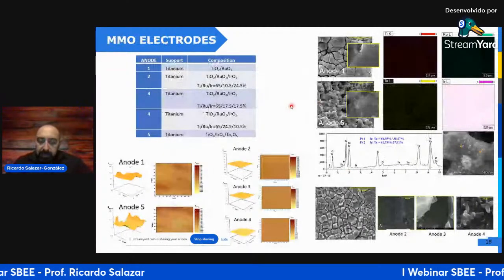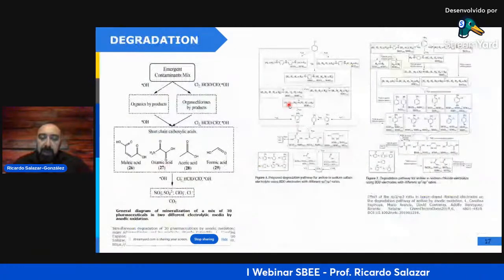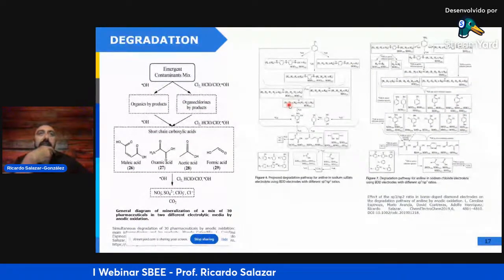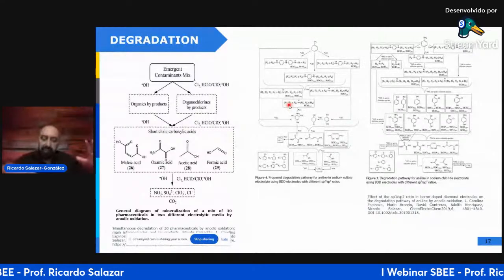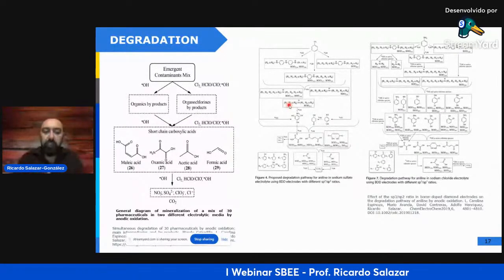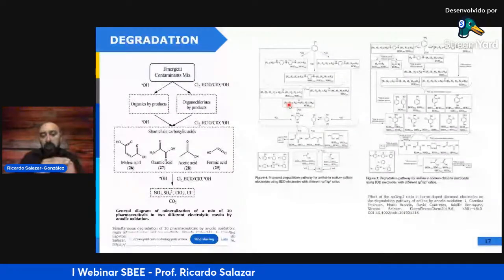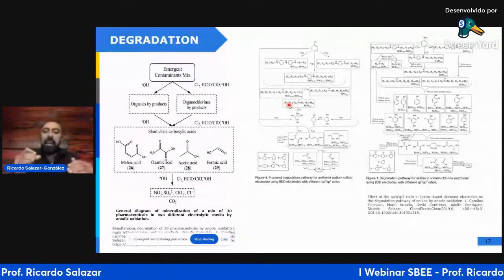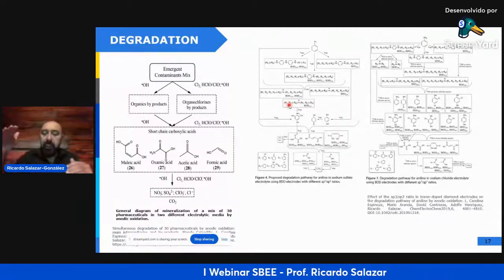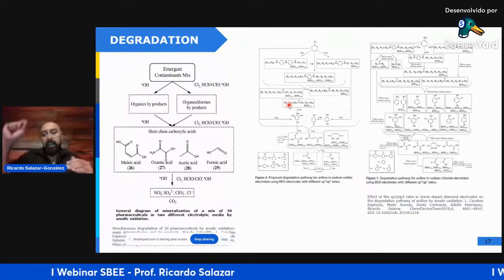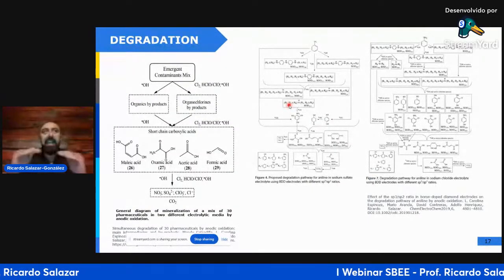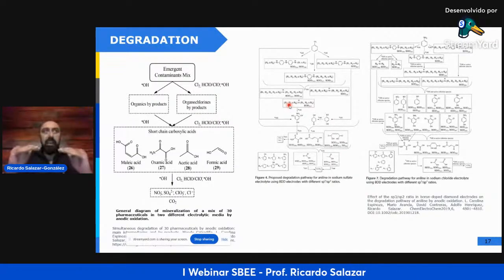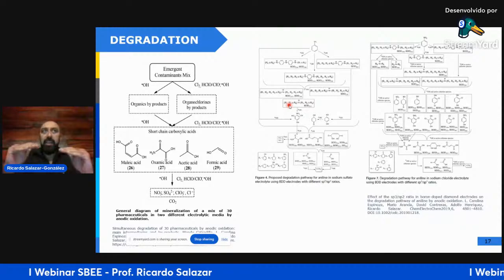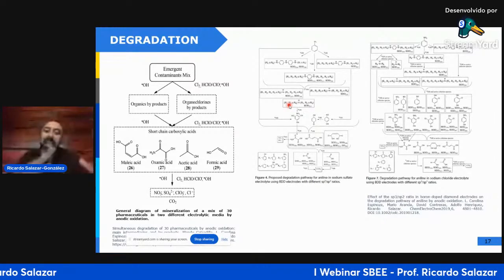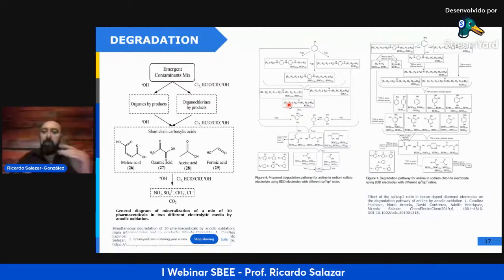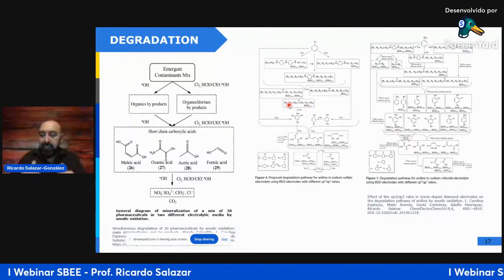Well, the main conclusion for the BDD electrodes is that we can modify the efficiency in the production of hydroxyl radicals if we modify the electrode surface, increasing, for example, the quantity of diamond on the surface and the doping of boron. And if we change the support of the boron doped diamond electrodes, we can't change the surface, but we can decrease, for example, the resistance to the charge transference.